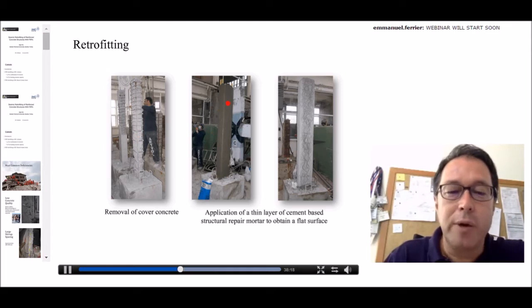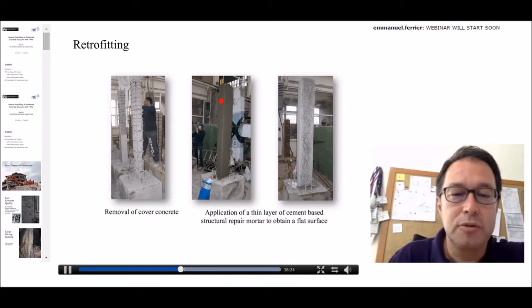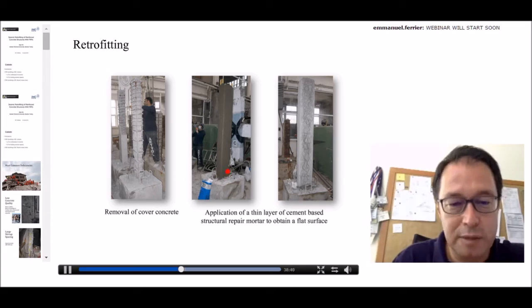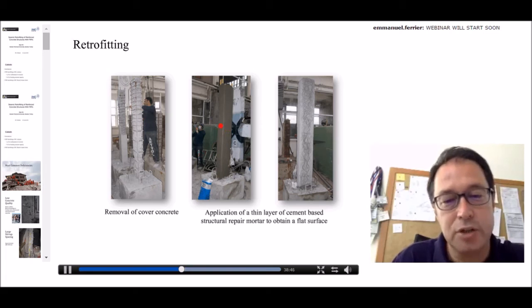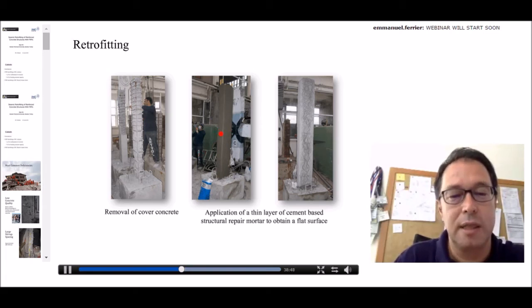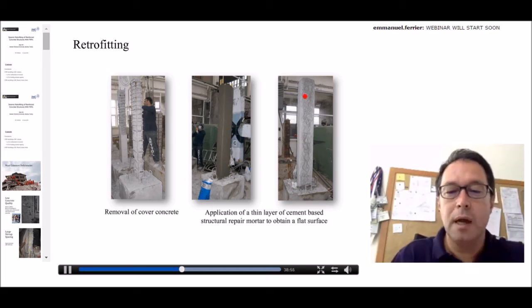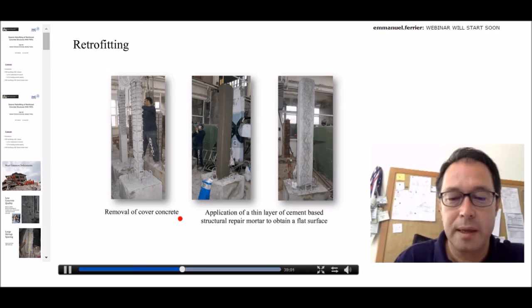After that, we just apply a very thin layer of cement-based structural repair mortar to obtain a flat surface where we are going to place either laminates or rods to retrofit the column in terms of flexural resistance. So we have this kind of mortar here. This is very, very thin, only covering the main bars and the transverse bars. So now the section of the column is smaller than its original size, because not all the cover thickness has been produced again. And some roughening on the surface to have better bond with the next stage.